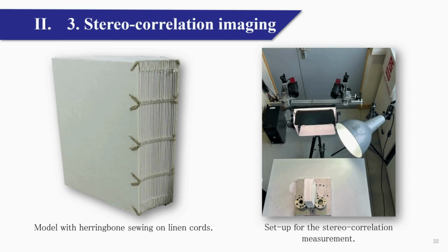Finally, an experimental test by stereocorrelation was conducted by the Solid Mechanics Lab to calculate the deformations and displacements of a surface under mechanical stress. The stereocorrelation technique allows to measure the displacement between 2 images of a surface, using 2 lenses to calculate 3D deformations. The model provided by the Conservation Studio is a paper text block sewn using herringbone sewing onto the linen cord. An adhesive tape with a pattern of dots is applied to the spine. This allows to calculate the displacement and deformation of the spine at the opening. The surface profile was reconstructed using digital image correlation.